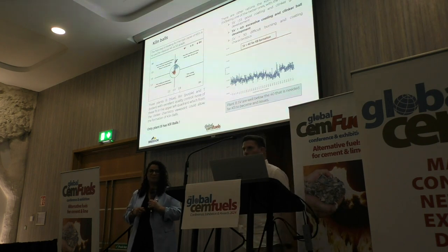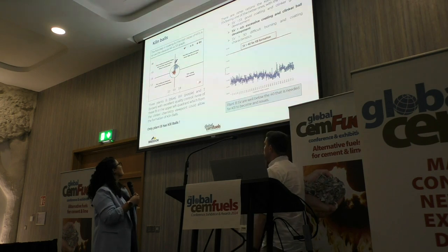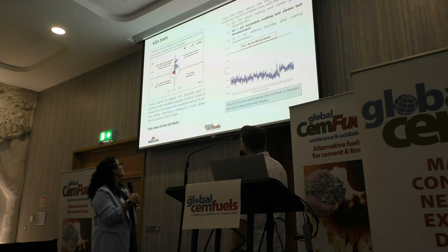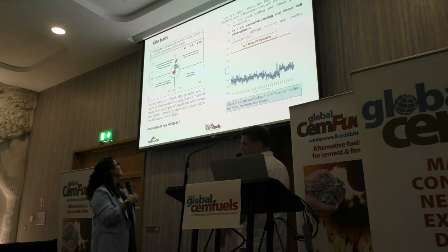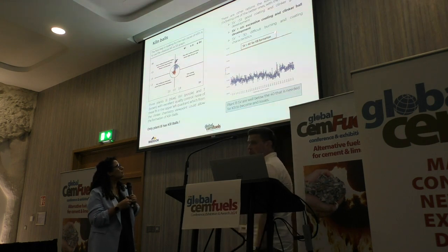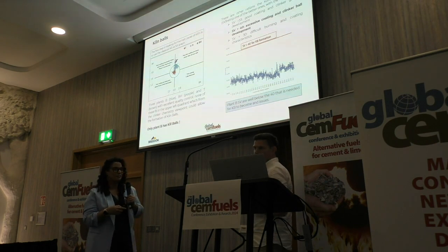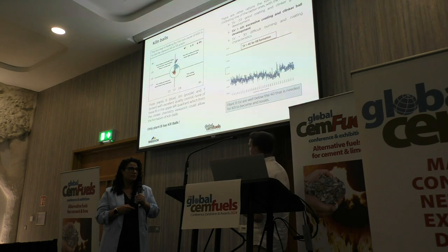Just as a basic analysis tool where we first set off, as you can see from the basic AR versus SR table above, we have shown three plants there, plant B, BH and T. In general, the best place to be is right in the middle. All plants are quite in control of the process, but plant B has kiln balls, and that plant B is Kinnegad Breedon Cement. Another tool that you can use is the SV sum. In general, if you're over an SV of 40, you are more prone to kiln ball formation. Our current plant, we're running close to 33. We are in a good place. It's just to highlight general things, but you can still have kiln balls, and this is why we are trying to investigate to see what is the root cause behind them.